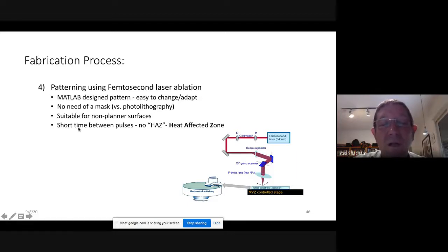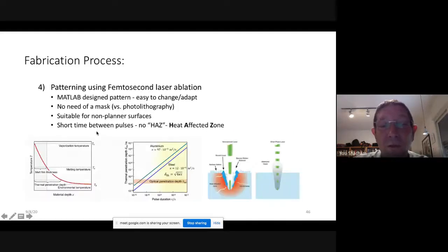The pulses are, as I told you, about 270 femtoseconds. Because the time is so short, we have a huge energy density per unit area. So the ablation is so fast that the rest of the substrate does not heat. Because of that, we don't have damage to the polymer under it. I'm going to show the structures later. Practically, let's focus on this part.